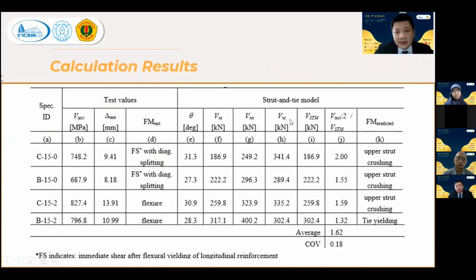And we can see that the strut and tie result is taken as the smallest between the strength of the strut, nodal zone, and tie in here. Okay. And we can see the strength ratio is 2, 1.55, 1.59, 1.32. So overall, the average is 1.62 and COV is 0.18. So we can argue that this result is quite conservative, but it actually has a good COV.